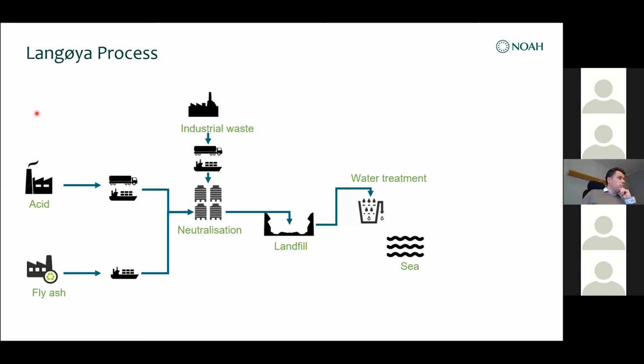Our two main waste streams are acid, which is sulfuric acid, a waste product from Kronos Titan in Fredrikstad, where they produce titanium oxide, which is a white pigment. After this process, we get sulfuric acid, and the concentration is around 25%. And in numbers, we're talking about 200,000 cubic meters per year, so it's quite a lot of acid.